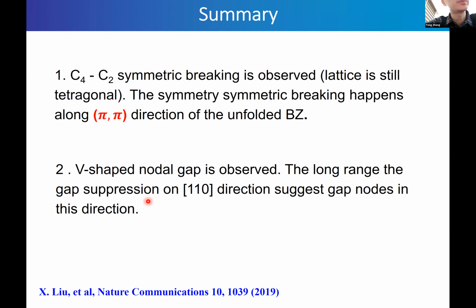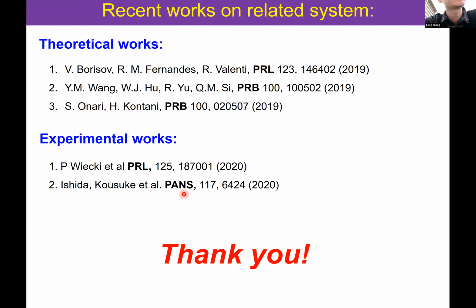So in summary, we observe a C4 to C2 symmetry breaking, and it's along the pi direction. And we observe the V-shaped nodal gap and the long-range gap suppression along the 110 direction, which suggests the gap nodes are in this direction. It's more consistent with d-wave pairing. Okay, here I will just list the recent work on related systems. Yeah, thank you.